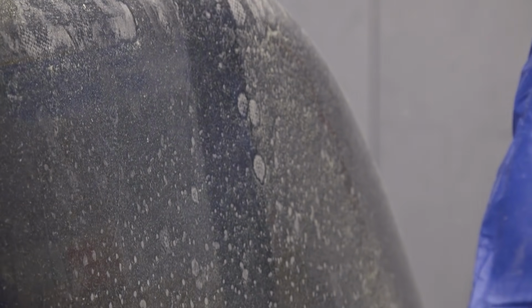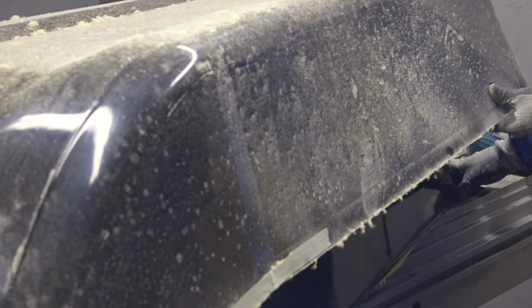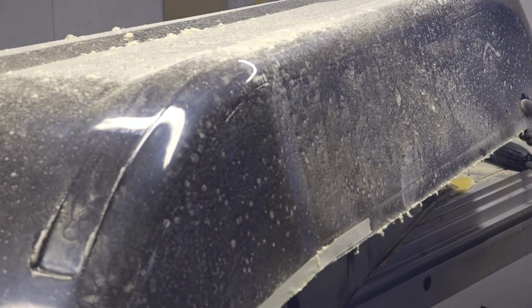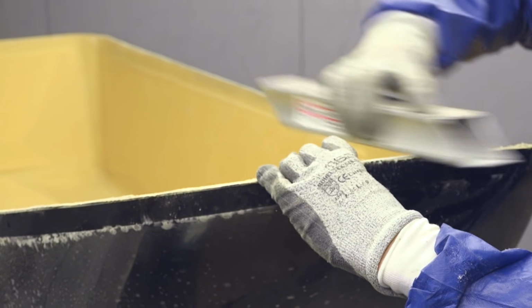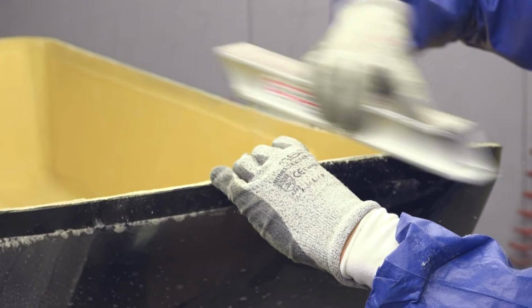Kevlar is not only tough to cut as a dry cloth, but also as a finished laminate. The cut line will invariably fluff up. I find that the easiest way to clean up the trim line is to sand it into shape with a permagrit block, and then remove the fluff with a fine 800 grit wet and dry paper.